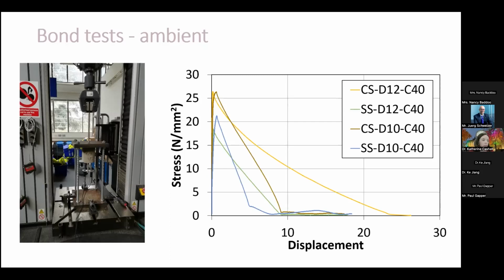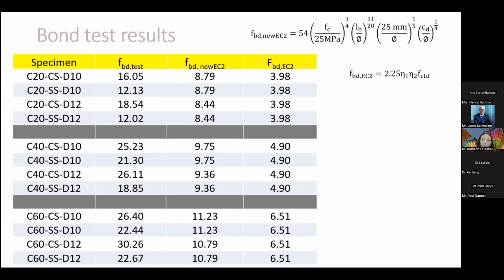We took those bond tests, and I won't go through this in too much detail, but we've compared the bond strength of the stainless steel with the European, so that's the Eurocode 2 bond rules, and stainless steel is still completely on the conservative side. Although it doesn't develop quite as high levels of bond strength as carbon steel, it is certainly still well above that which is required in design.